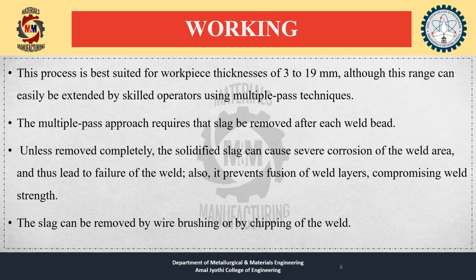If the slag is not removed completely, this can cause severe corrosion of the weld area and thus lead to failure of the weld. It prevents fusion of weld layers, compromising weld strength. The slag can be removed by wire brushing or by chipping of the weld.